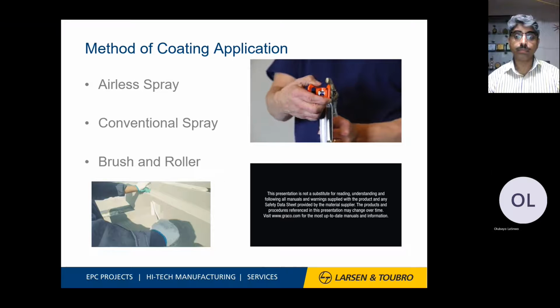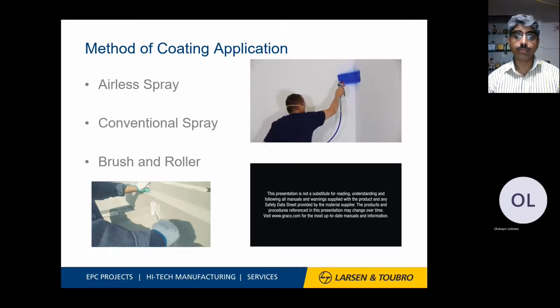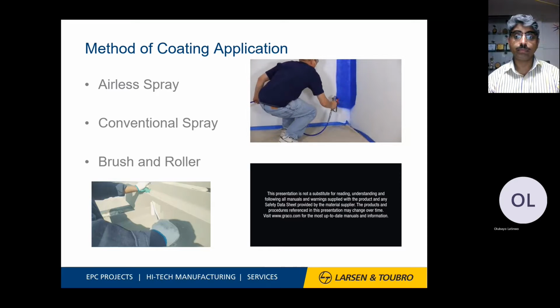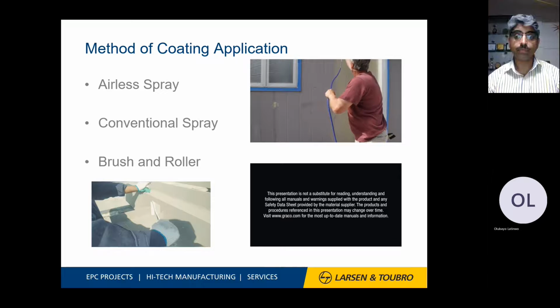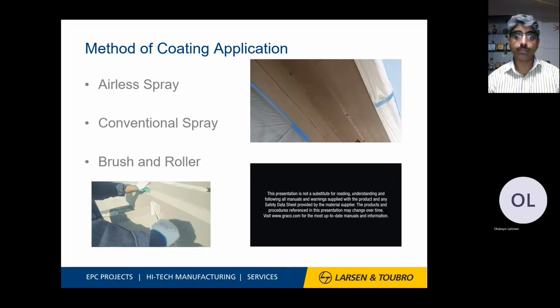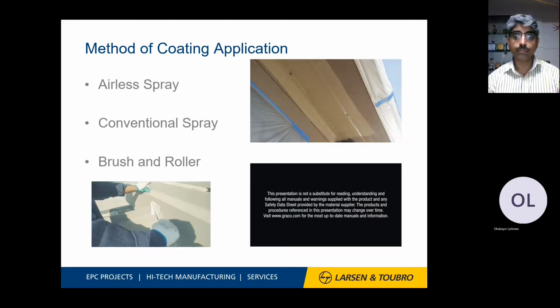For vertical corners, turn your guard so the spray tip is on the top and aim your gun into the corner. Spray along the corner, applying an even amount of material along both sides. Typically, when painting, it's best to start at the top and work your way down. Begin by spraying any eaves or the underside of overhangs. The direction you spray is determined by the construction. As a general rule, spray horizontal and make sure you direct the spray up a little to spray the bottom lip of your siding.